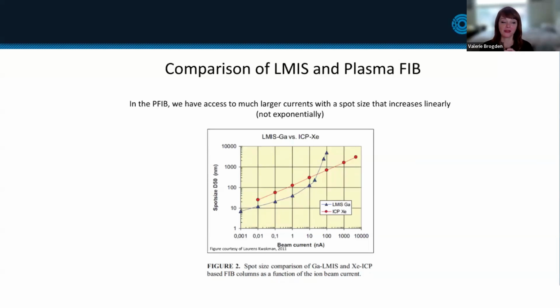So one thing you can do is, of course, put a really thick cap layer on top. If the very first thing that the beam sees is something that's really rough and topographical, then the rest of your cut is going to be rough and topographical. But if the very first thing that the beam hits is something that's smooth and even, that'll help a lot. So sometimes I've even done up to 8 microns of tungsten deposition in my PFIB before I start a cut. You know, especially if it's a long cut.